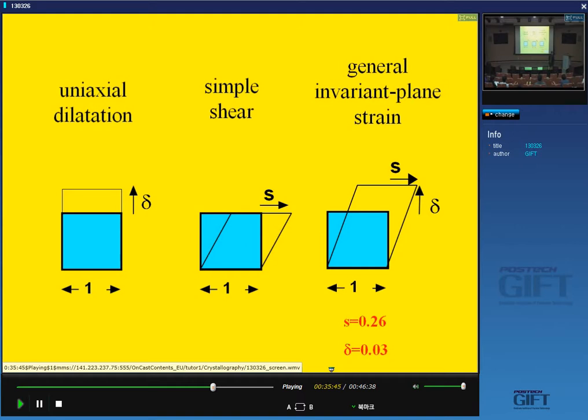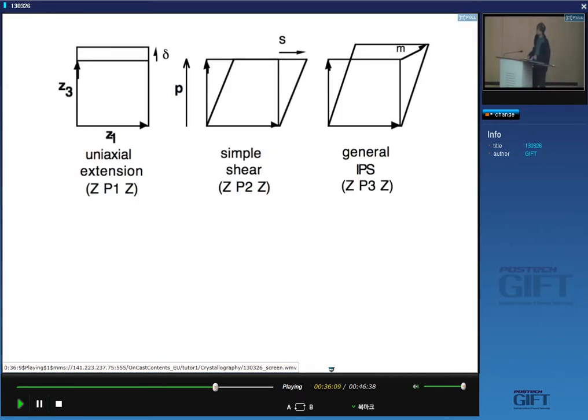Okay. So this is the kind of deformation we are interested in, and these are typical values of the shear strain and the volume change associated with phase transformations in steels. Now, I want to derive the deformation matrices for these operations. So I'm going to choose some very simple axes. I'm going to define my z1 axis on the invariant plane, and the z3 axis pointing vertically, and z2 is out of the plane of the board. So just by looking at this, I could write down the deformation matrix,